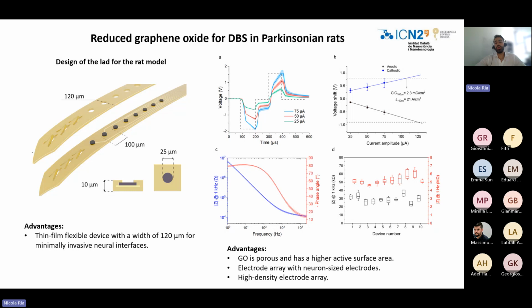So this is due to the special structural and electrical properties of the electrodes, because the porosity of the electrodes increases the active surface area. So even the area of the pores is accessible to the ions. In this way, the electrodes behave as capacitors, so they can store and inject charge, and this brings to a very high charge injection limit.